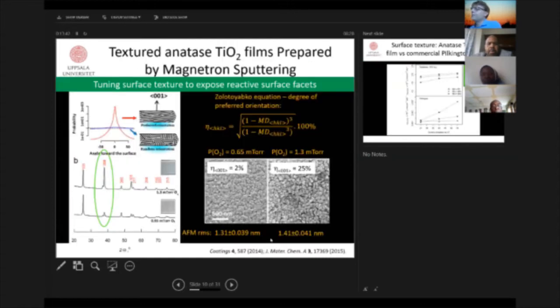What we have done is that we have used magnetron sputtering technology and come up with a scheme to orient the surface texture of these films. As you may know, sputtering technology is an industrial process. This is one of the major processes to make thin films. So this is clearly an upscalable technology. And in these electron microscopy images, this is how it typically looks. From there, you cannot see the surface texture.